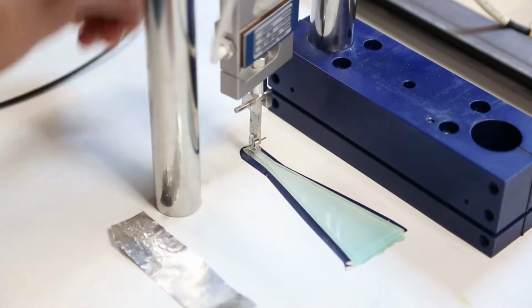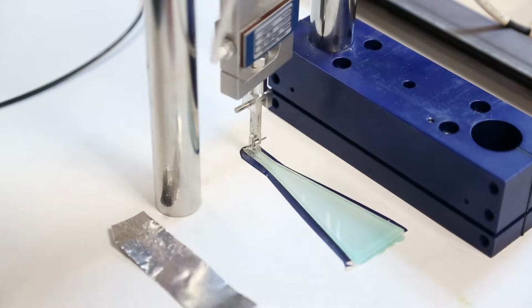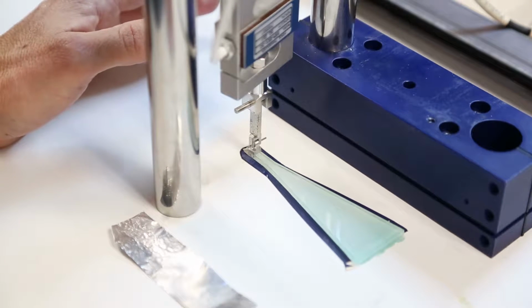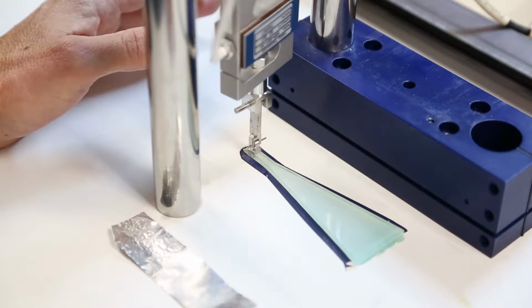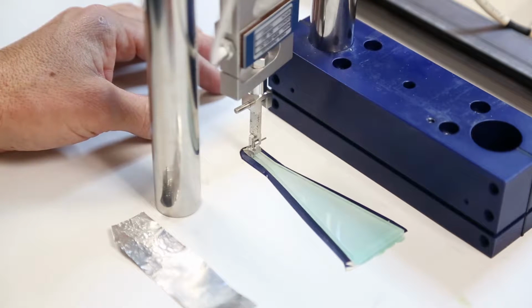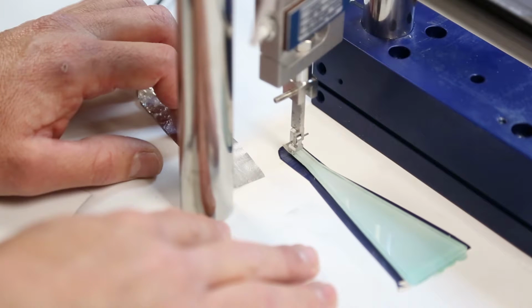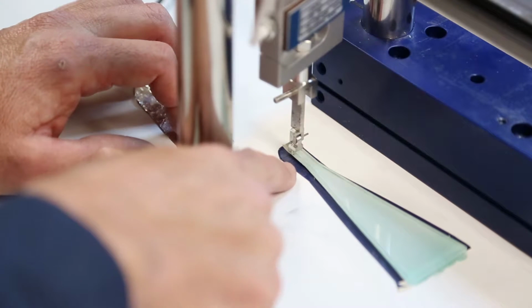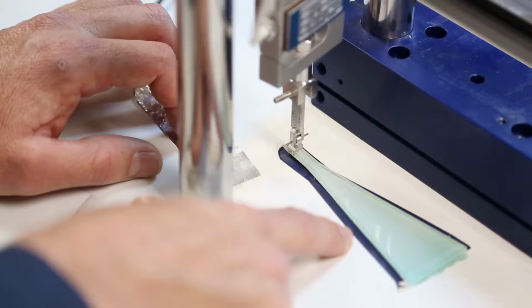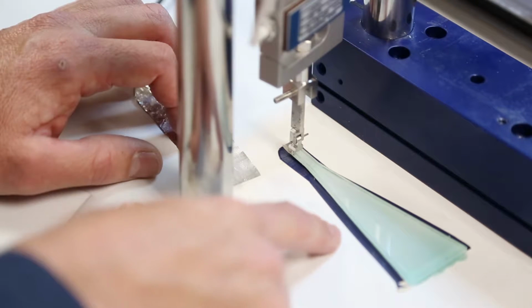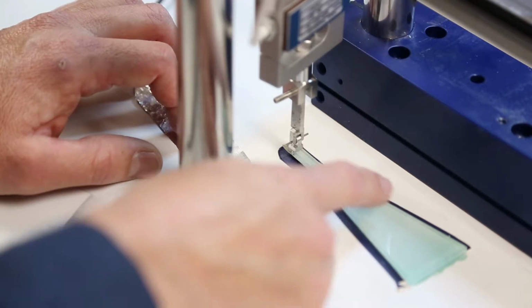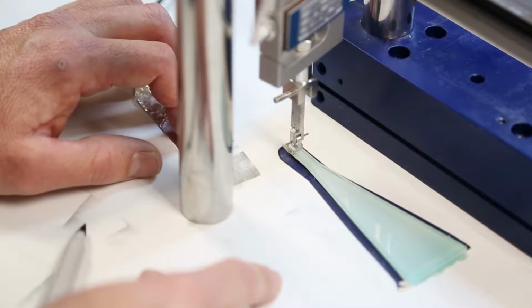The program for our load frame is a simple displacement rate control at 10 microns a second. In fact, for all width-tapered cantilever beam measurements, we always run at a displacement rate of 10 microns a second. I've started my load frame to run at 10 microns a second, and now the debond is starting to propagate slowly down my beam. I'll want to let it run until the debond is approximately halfway down my sample.